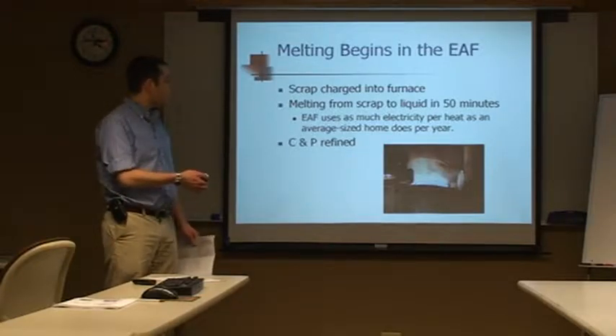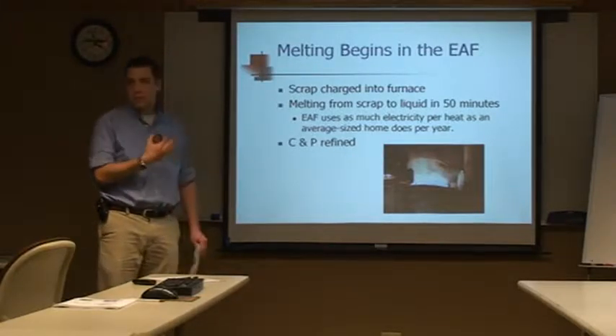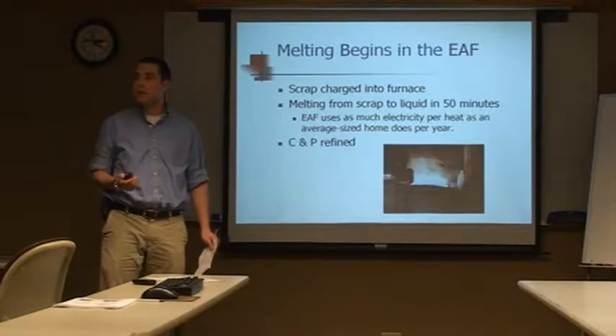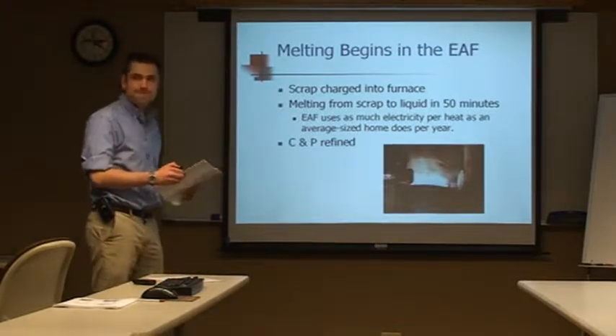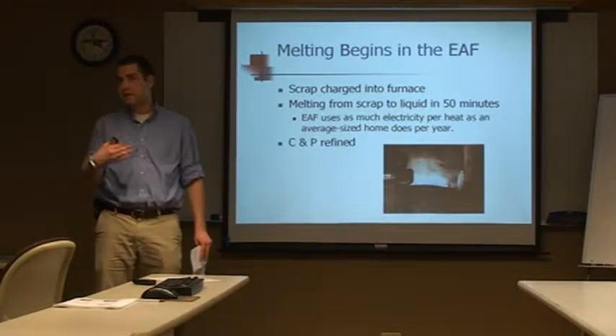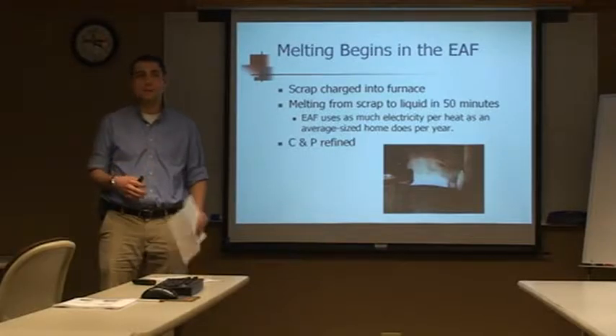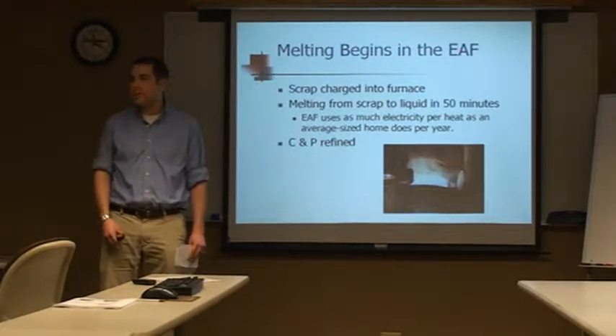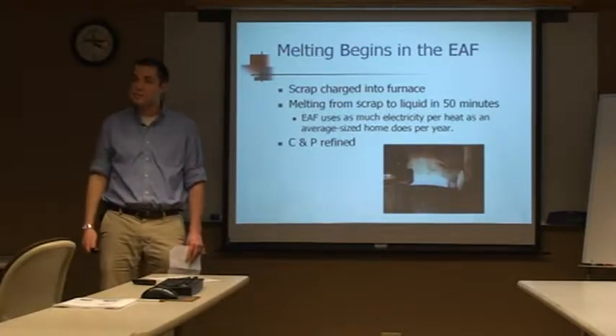But in general, we can just use the oxygen blowing to get the phosphorus down to the kind of levels that we're looking for. What do you guys do with the slag then? We collect it in a slag pot, and I think that we send that out as a waste product. Underneath our arc furnace, there's a tap hole where the ladle taps, and then back behind here there's a slag pot.